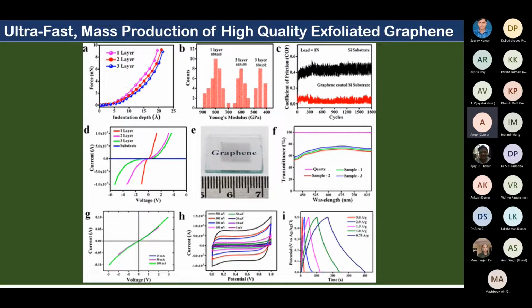So we did various studies, then again an electrochemical study also, to understand the GCD curve and the CV curve. And then we found that our graphene shows properties comparable to graphene produced by other techniques like ball milling and CVD techniques and all. So this was the proof of concept which we have produced. This entire work is giving the confidence that the plasma spray technique can produce high quality graphene, right? Follow-up work is also going on in this direction. But right now we are trying to commercialize this. We have got one project from Plasmatron, and we are trying to commercialize this whole technology.